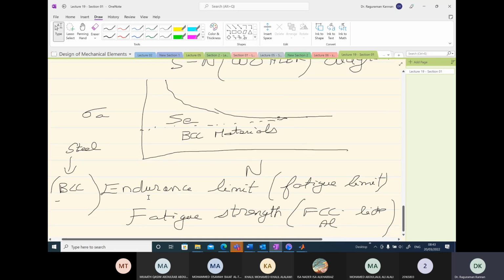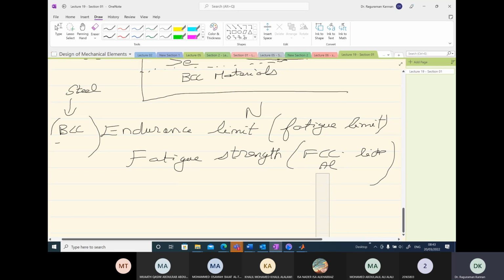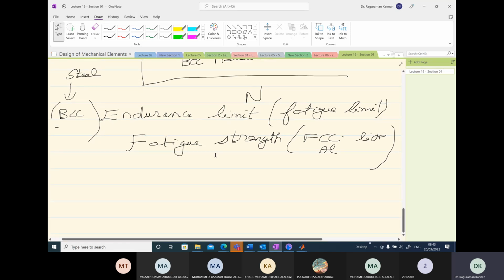Okay. Endurance limit is the limit below which the material will have infinite life. On the other hand, fatigue strength does not have any property like that. Below fatigue strength, again, you will have only finite life. Okay. There is no infinite life for FCC materials like aluminum. So clearly you can see the advantage of using steel over materials like aluminum. Aluminum is lightweight, but again, it has finite life below fatigue strength value. However, steel, if you design your component in such a way that your stress lies below the endurance limit, then the component will have infinite life even under fatigue loads. But the disadvantage is you have very high density.